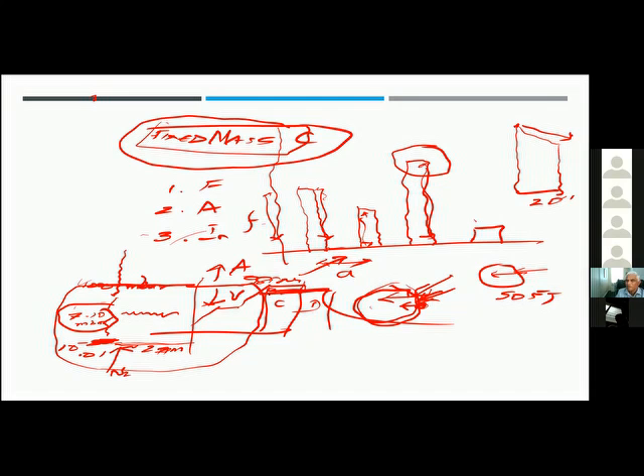The Stefan-Boltzmann equation kicks in only at about 1000 Kelvin, about 720 degrees C. So in order to ensure that reheating of the load also happens better, we do partial pressure. And then when we fill in acetylene, it will toggle between vacuum and partial pressure. As the acetylene gets consumed on the surface, the diffusion takes as much as is consumed. This will be an equilibrium that is maintained. So the partial pressure is only there till the load is preheated, till it reaches about 720, 730. When convection is no longer needed, it goes back to 980 for full austenitizing temperature, and then it's taken over by diffusion and power.